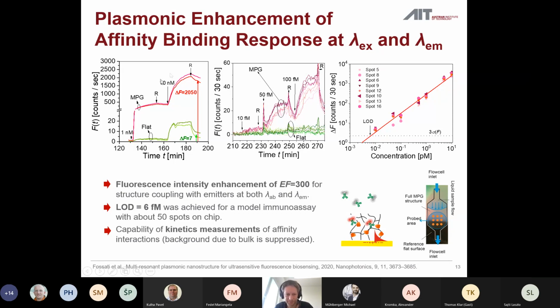And in this slide, you can see the comparison of the fluorescence signal intensity, which was measured in time upon titration of different concentrations of the analyte on the surface which was flat, and on the surface which was structured. And the structured surface was designed to provide this amplification of the measured signal, and you can see an increase by a factor of about 300, which, if we then go for small concentrations, allowed us to push down the limit of detection to about sub 10 femtomolar concentrations, while on the non-structured surface, we've seen just flat and basically no signal.